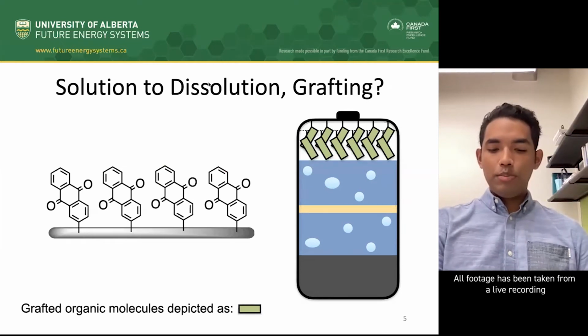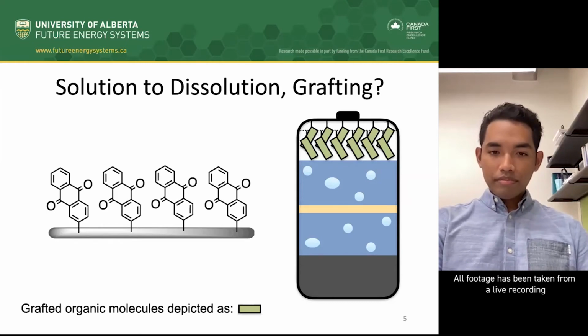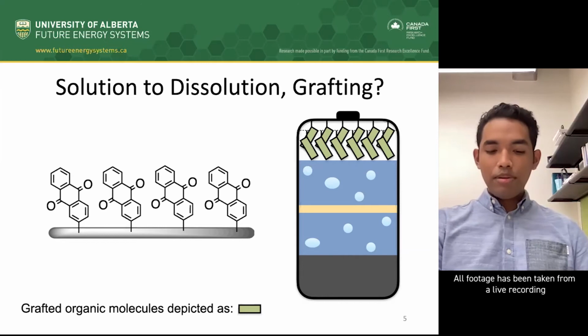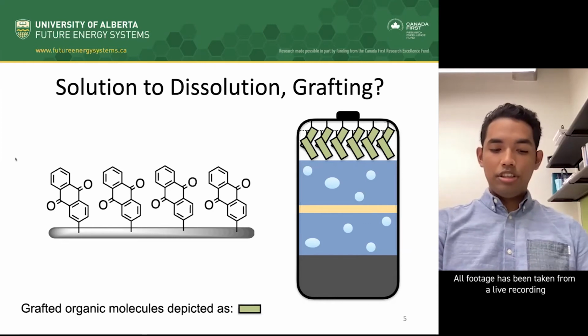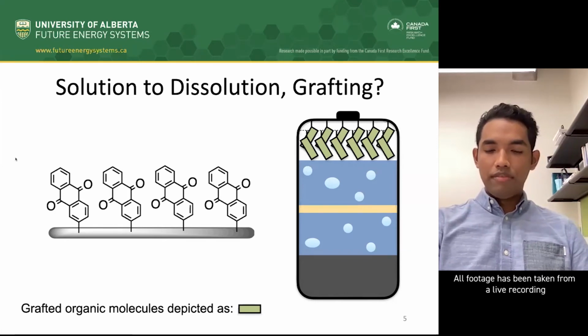Although significant effort has been put into solving the dissolution issue, this has mainly focused on materials and electrolyte modifications intended to reduce active material dissolution. We propose that grafting the organic molecule to carbon additives within the cathode through the formation of a covalent bond will stabilize the cathode by anchoring the active material, thus preventing or at least reducing dissolution and subsequently capacity fade. This architecture is shown in the figure on the left. The animation on the right depicts the reduced dissolution of this architecture.